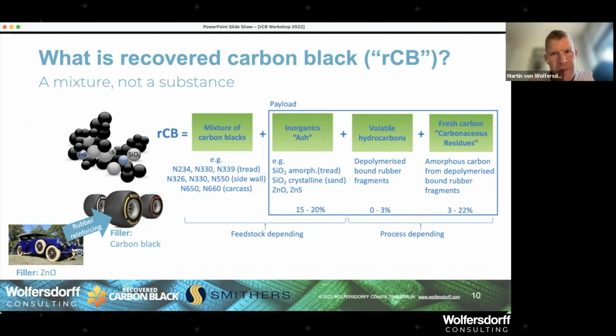So we can manage through pyrolysis conditions like temperature, residence time, but also the process type, how much we have of these components. We might have some volatile hydrocarbons. These come from the rubber that is broken down, but is still on the surface. That is the bound rubber around the carbon blacks that's very, very difficult to evaporate in the pyrolysis. And so we might have a content, I put 0 to 3%. It could be much higher than that, but a commercial recovered carbon black should not have more than 3%.